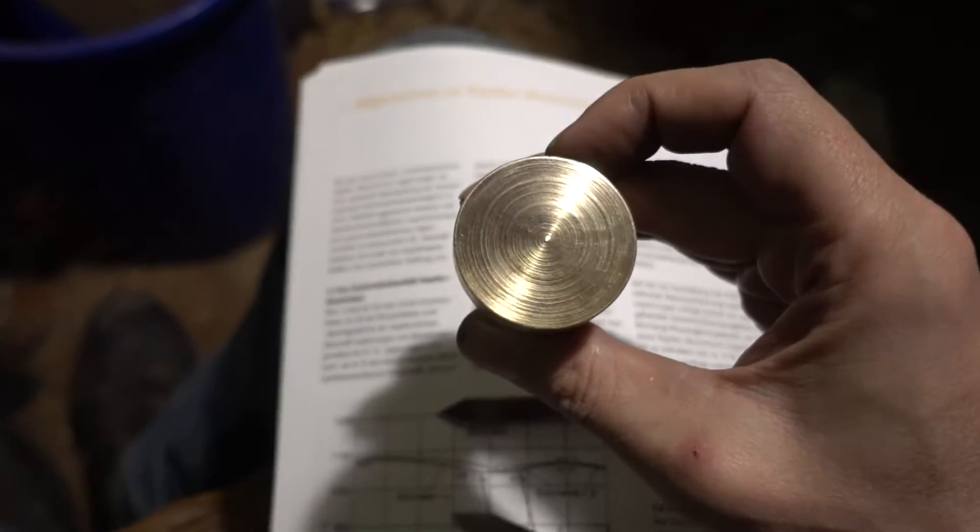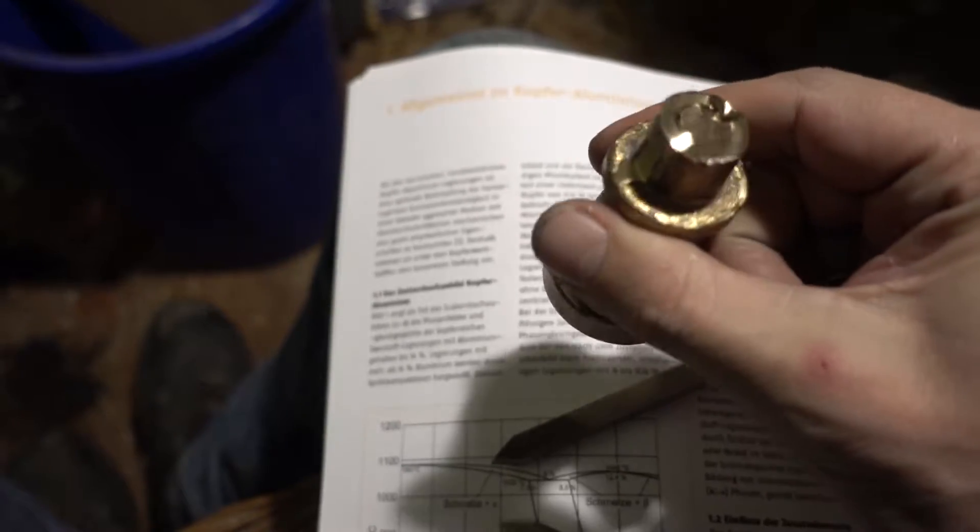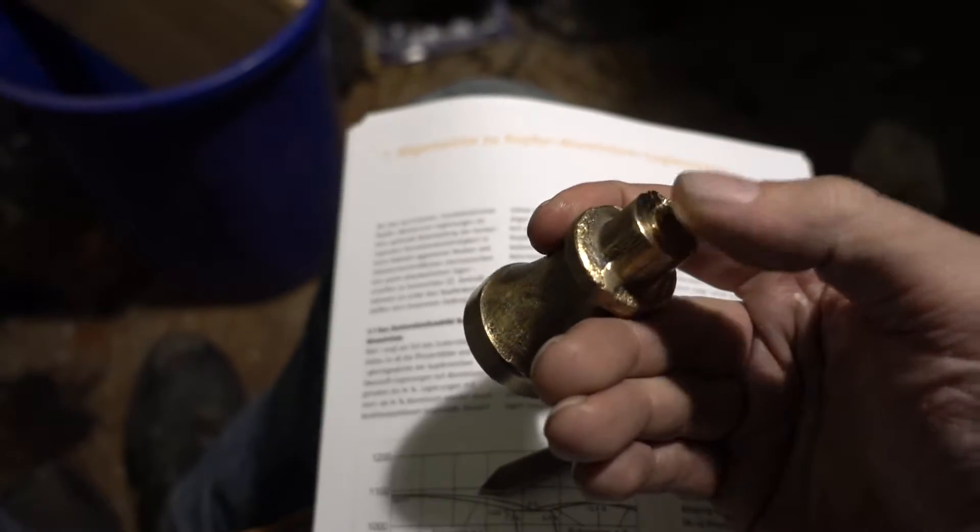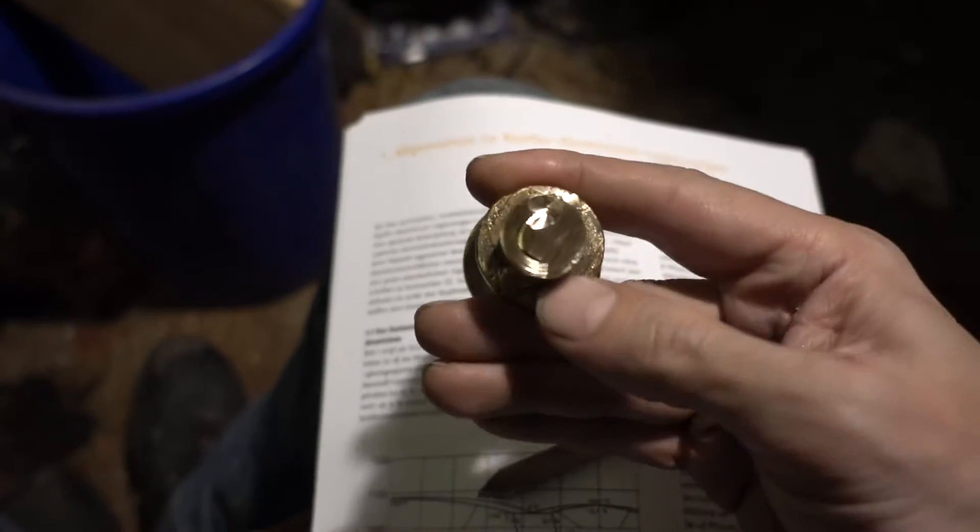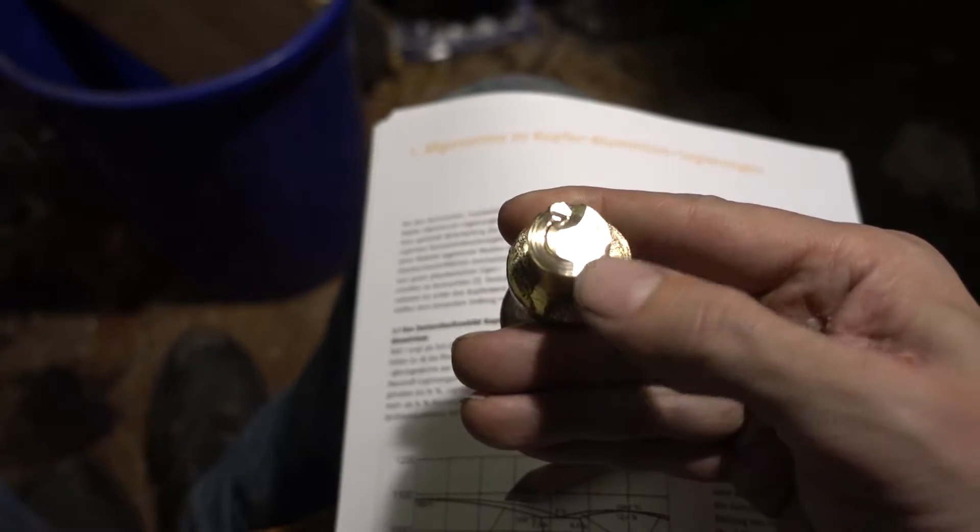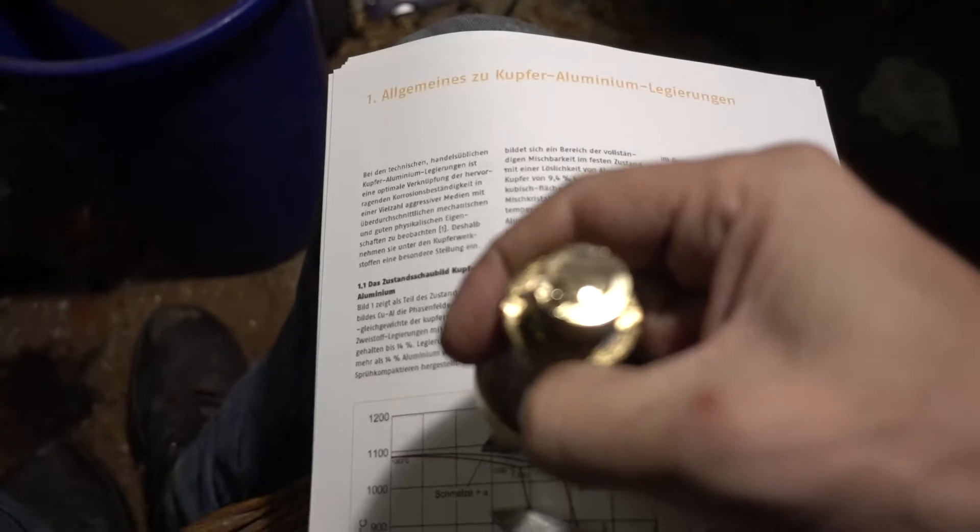It's not that nice of a material and it's also quite brittle. I realized when I hacked out the spur that the last part broke easily, and there's an extreme coarse grain structure there. So I think it will just be remelted.